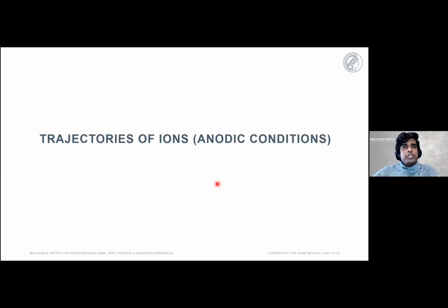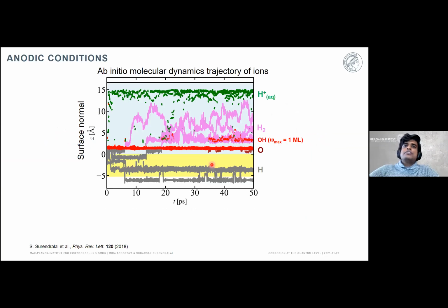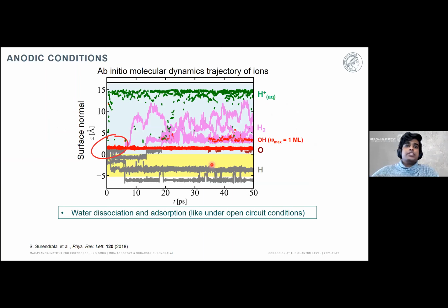What we do is we repeat the very same calculation, but we now apply potential control and make the magnesium more positively charged. In other words, we apply anodic conditions to the system. And we do the same thing. We again track the trajectories of the ions, and what we see now is something that is much more colorful. First of all, we do see the water dissociation and adsorption, which we also saw for the case of the open circuit conditions. We see that the hydroxyl layer, the OH layer, does not stop at 1/3 of a monolayer, but that it goes to a complete monolayer coverage on the surface of the magnesium. Of course, the hydrogen once again is able to penetrate the magnesium.